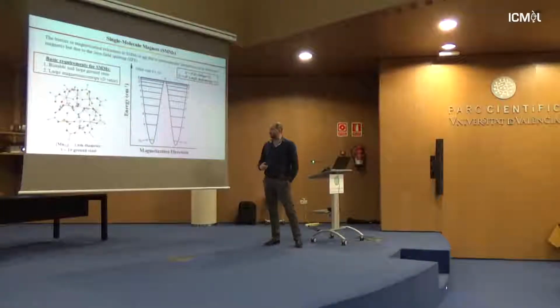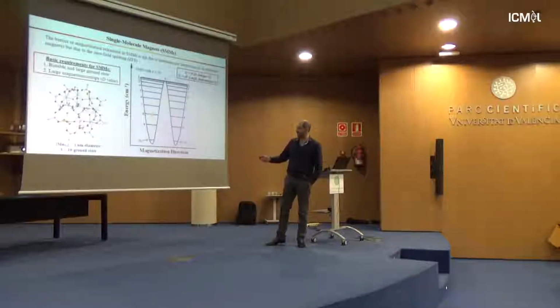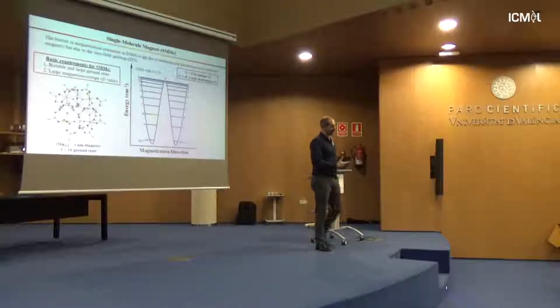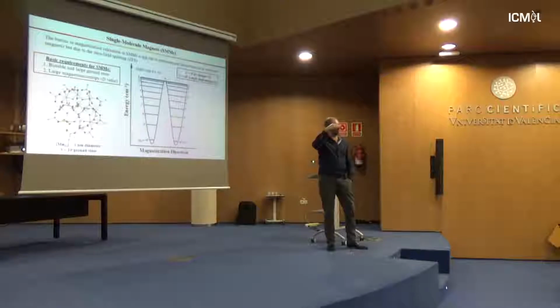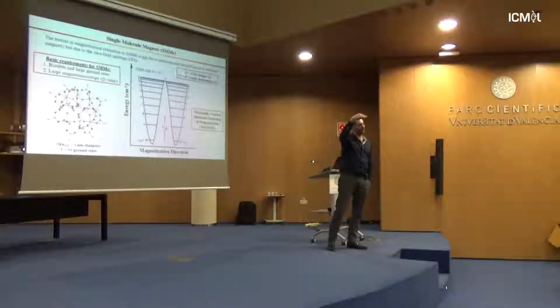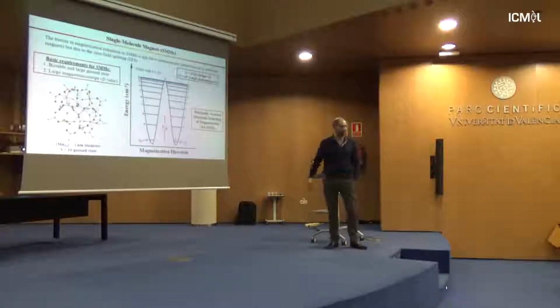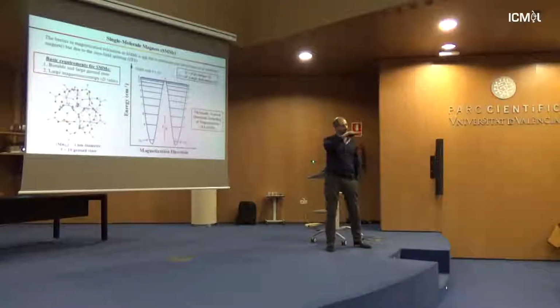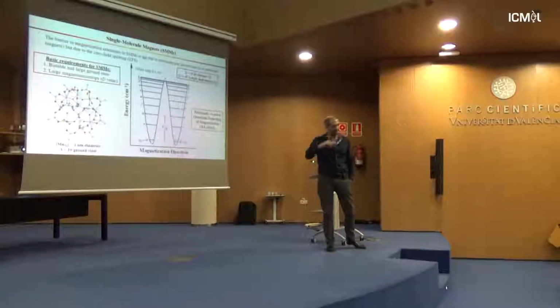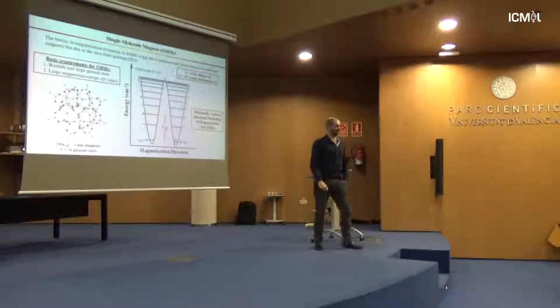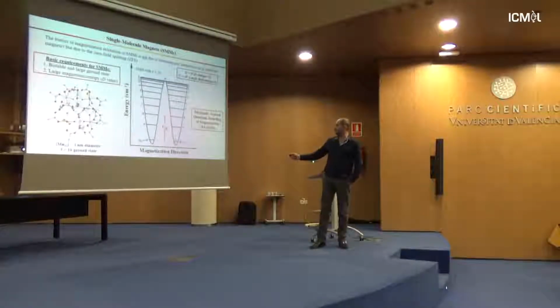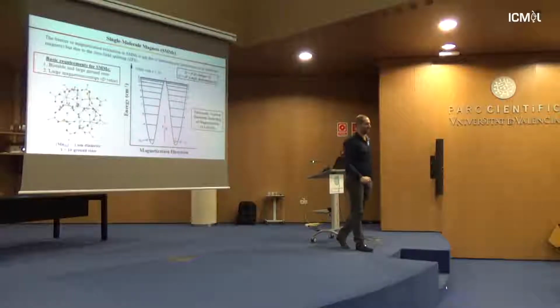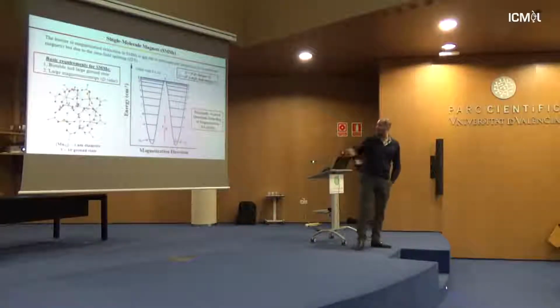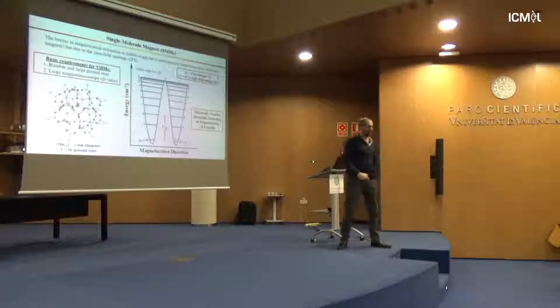That's because the most usual pathway is what is shown here as a representative example. The magnetization, as we say, can travel over those MS states. At some point it is frozen, or blocked, as we call it, and then it relaxes through the barrier to the MS state of the resonance structure of the same energy, and down to the ground MS level. This is called the thermally assisted quantum tunneling of magnetization, which includes both thermally assisted and QTM processes.